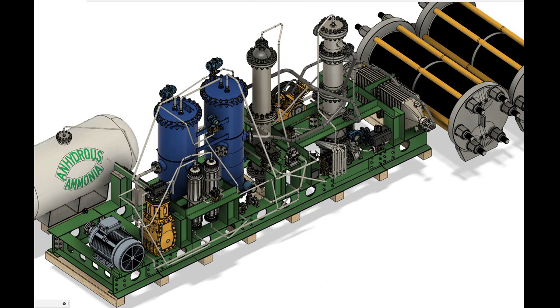In fact, some plants using the wustite-based catalyst in China run at only 15 megapascals. In our case, we want footprint reduction, so the pressure is most likely going to be kept above 20 megapascals, while space velocities are kept commensurate with this pressure. Virtually all ammonia synthesis catalysts are doubly promoted with alkali metals, but aluminum oxide is also used.